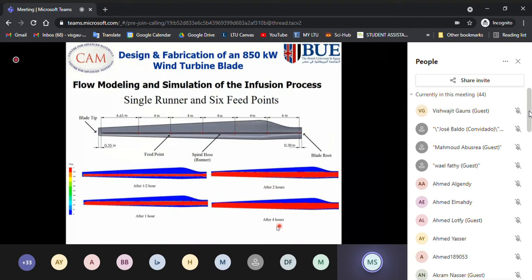You can see, after 4 hours in the first one, where we use a single feeding line with 6 feed points, the blue one is still a dry area. So we still have some dry areas after 4 hours. Basically, the infusion process using this strategy is not feasible.